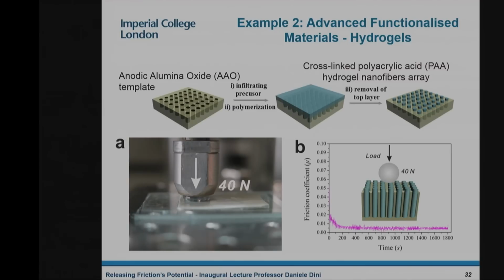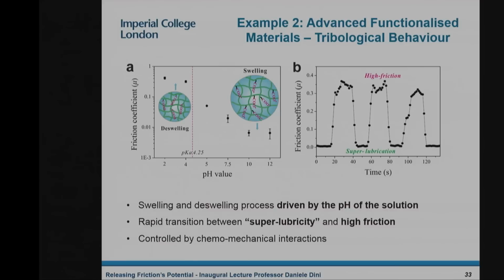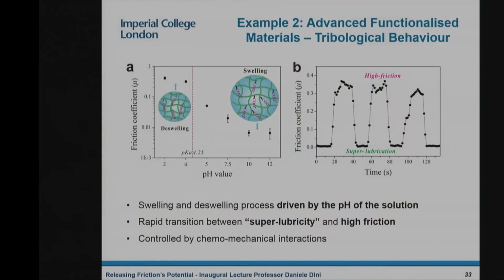Now, not only that, it looks like if you change the pH of the solution from very acid, very low values, to very basic, high values, because these hydrogels swell and deswell, there's a chemomechanical action in these hydrogels, and you can change your friction coefficient almost instantaneously to go from very low to very high. So you've got a way to switch friction in the contact between these systems.